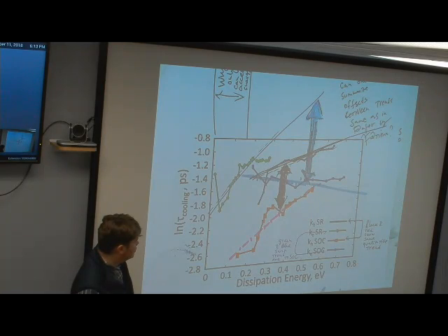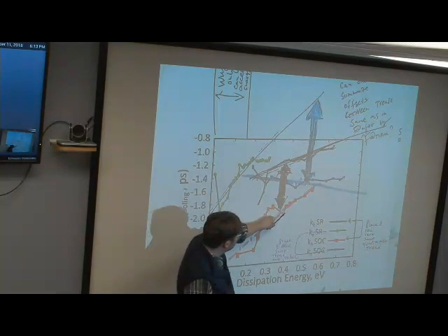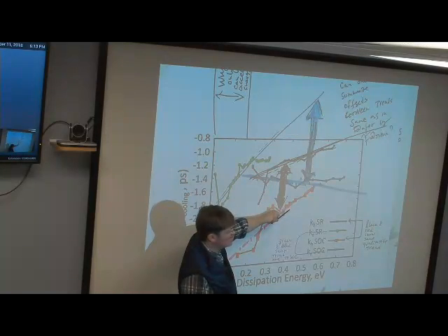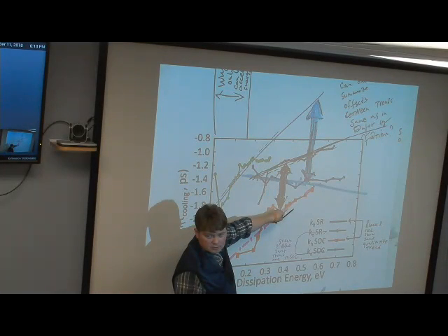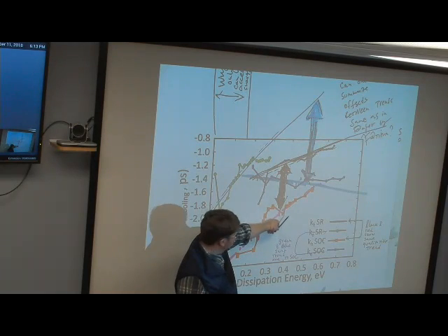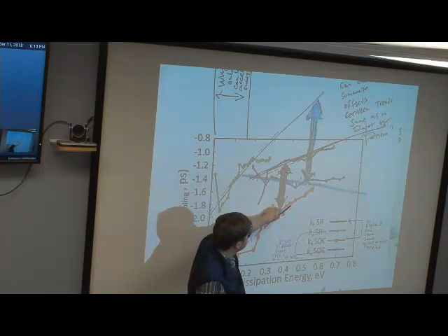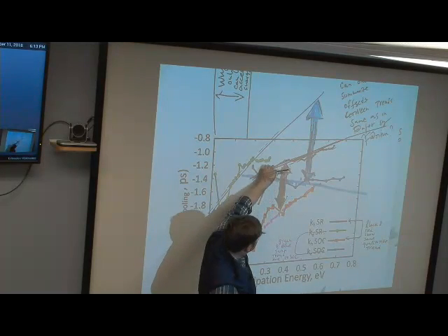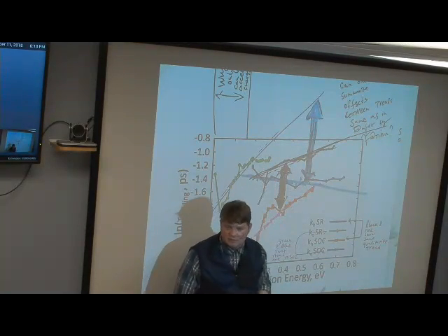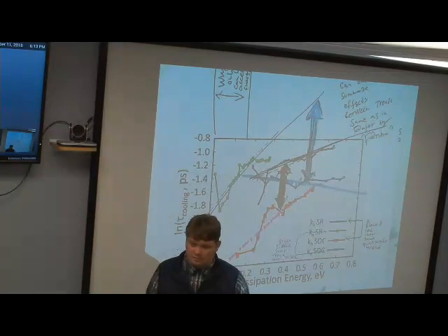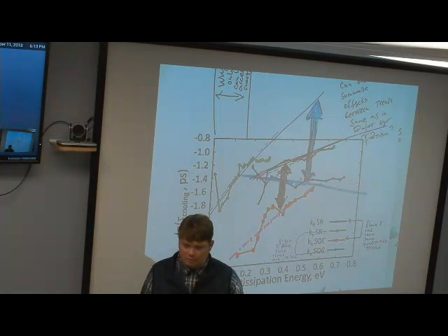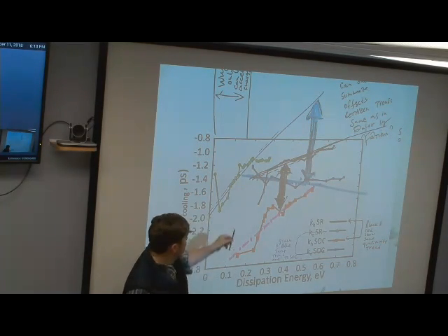So for holes, the presence of spin orbit keeps the same trend. The relaxation time increases with the increase of energy, so it matches the gap law, right? And by the way, the average offset between these two lines can be treated in the same way as Fatima has done it. After all figures in the main paper, she has a table where she gives the energy.